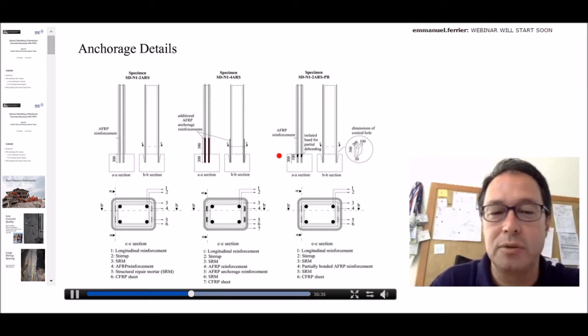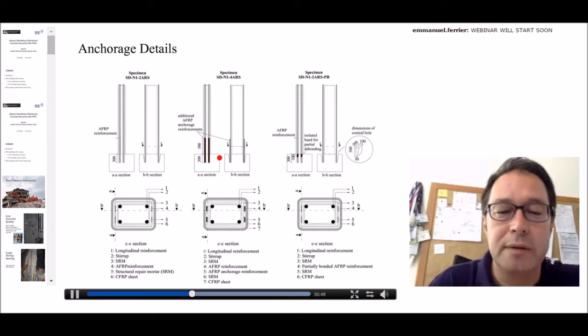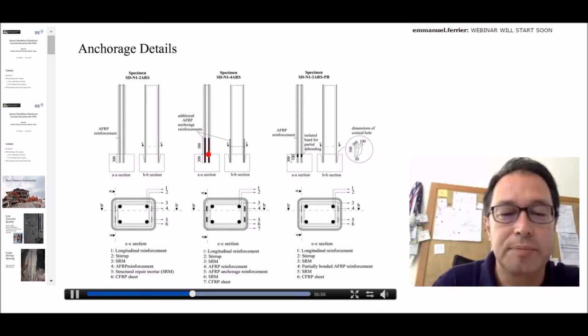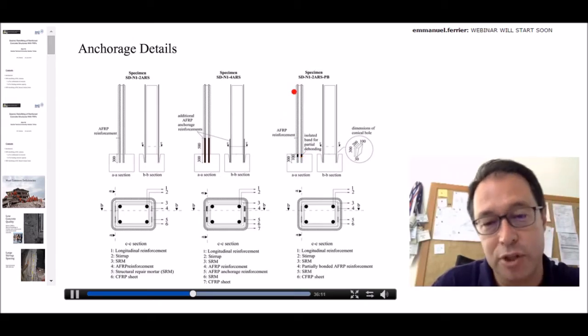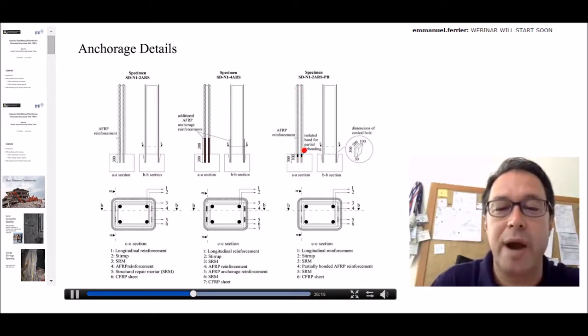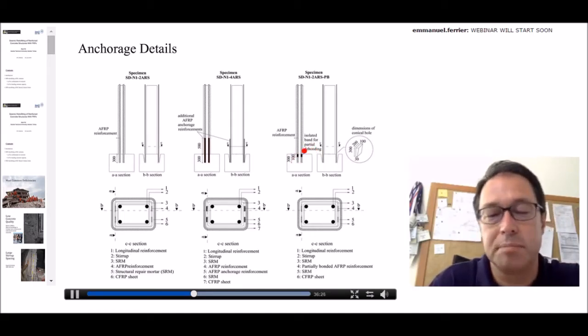And the final type that I'm going to present in this presentation is the one where we have intentional partial debonding of AFRP bars at the top of the foundation here. The reason is that we saw that in most cases, because of concentrated high strains, FRP bars or laminates are fractured at this point because of obviously the maximum moment. And we thought that if we could distribute the strains over a larger part of the FRP bars, strains will be less for the same top displacement. Therefore, the fracture of the FRP bars could be retarded to a certain level. So the target was that. And this type of specimen is called a partially debonded column, you could say.